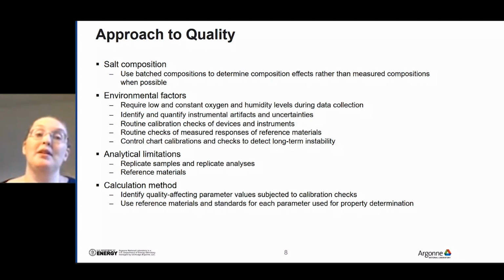So here's just a couple tips on how we approach quality for each of these factors. For salt composition, we like to use batched compositions rather than measured compositions. Measured compositions tend to have a higher analytical uncertainty than, say, the balance you're using when you are actually measuring salts and mixing them. So that seems more accurate. For environmental factors, we require low and constant oxygen and humidity levels. We do identify and quantify all instrumental artifacts and uncertainties. We routinely check the calibration of devices and instruments, both complex instruments like the DSC and simple ones like calipers and balances.